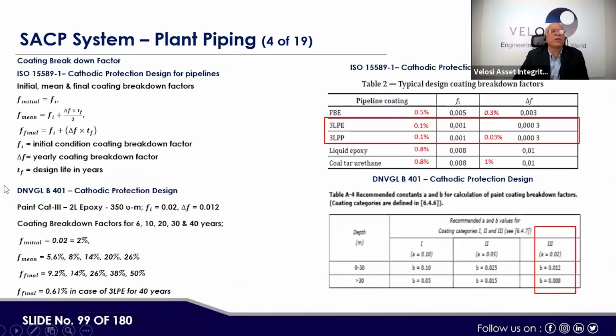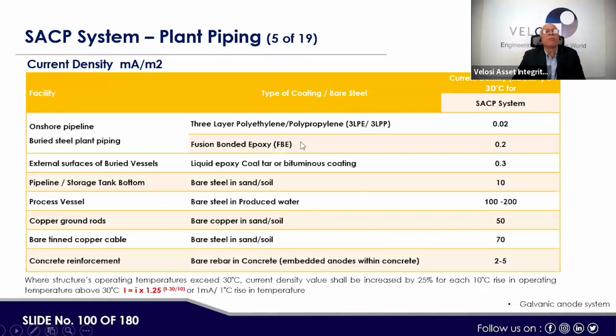Here, calculation wise, the coating breakdown factor is calculated with this equation: F initial, F mean, F final, and equations are there. The type of coating is 3-layer polyethylene, and these factors are calculated. Then accordingly, there is also a DNVGL formula, another way of calculation. Here, current density in milliampere per meter square: onshore pipeline, buried steel plant piping, fusion bonded epoxy, and external surface of buried vessel 0.3. Pipeline and storage tank bottom is 10. It is taken from here.